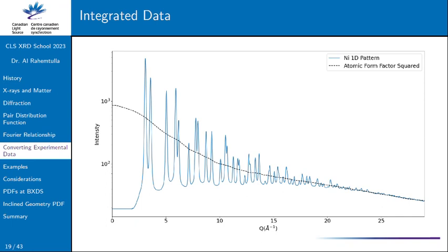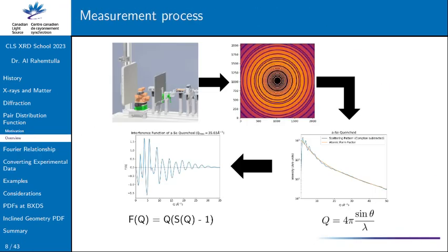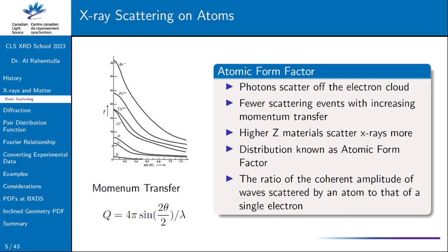If I was to go back a few slides, you can see where it has different ions, like the calcium 2+ and the chlorine minus, right? They're isoelectronic. So at zero, they're the same because they're the same number of electrons, but then they differ slightly because in the calcium one the electrons are more compact, but the chloride ones are more diffuse. So the more compact it is, the less destructive interference you get. So even though they're isoelectronic, they don't scatter exactly the same at the same angle, because the more compact atom has less internal destructive interference.